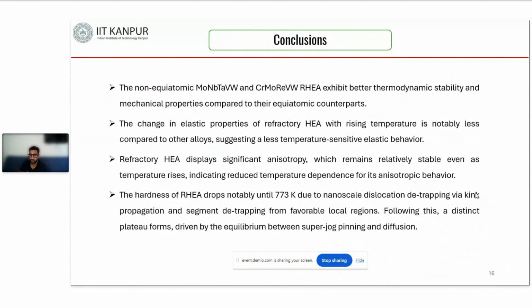So I can conclude in my talk that the non-equiatomic alloy is giving better thermodynamic stability and mechanical properties compared to its equiatomic counterpart. Its anisotropic behavior is less temperature dependent, and this alloy has better thermal stability. Its hardness values initially drop, and the reason is that dislocations are able to move from their locally favorable region with the help of thermal assistance, followed by a plateau region where there is an equilibrium between superjog pinning and superjog diffusion. So thank you very much.